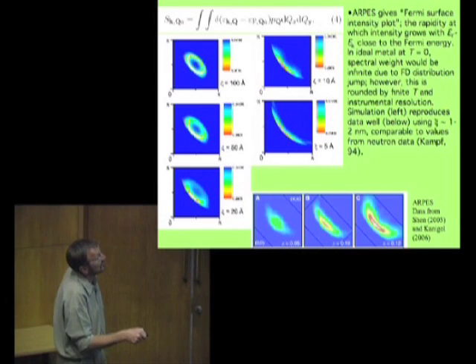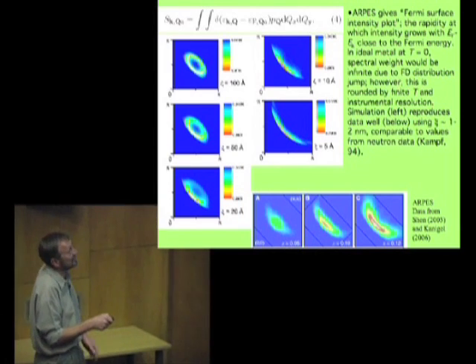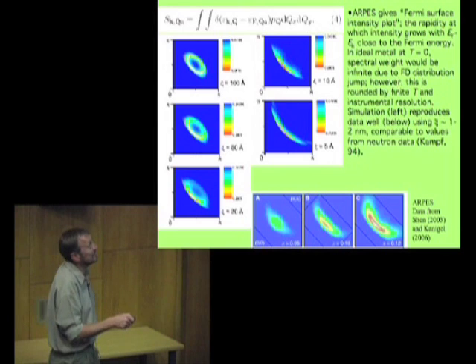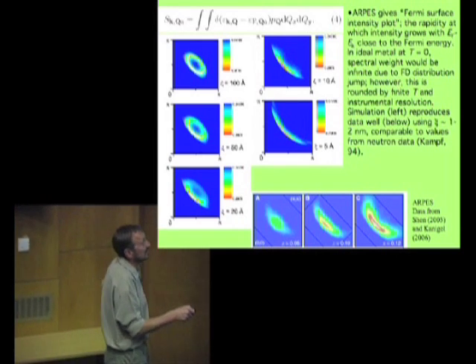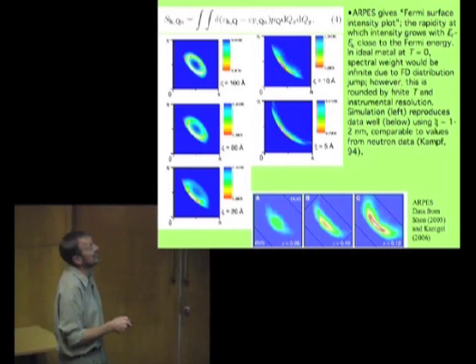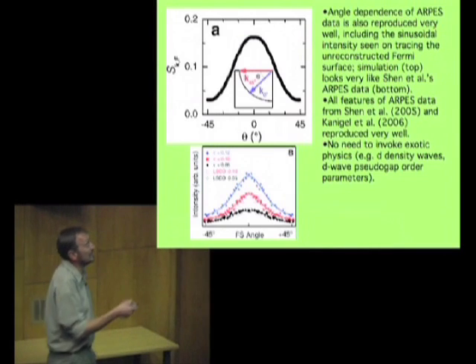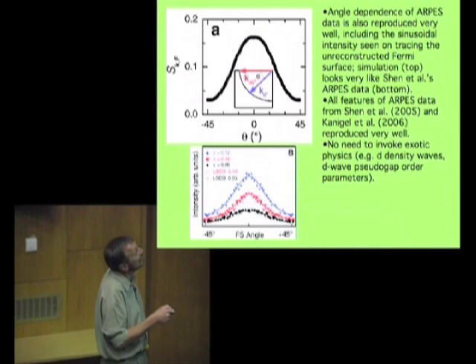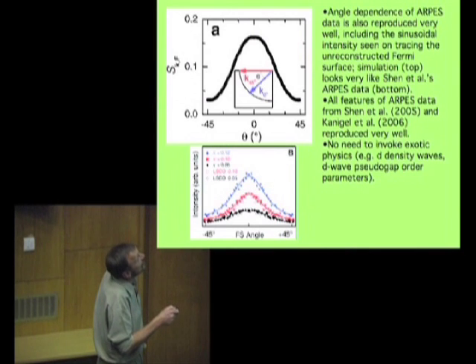So this simulation, which is done just using our measured Fermi surface and that statistical model, looks very much like the ARPES data that people like ZX Shen get. And this is using a very similar antiferromagnetic correlation length to that measured in the neutron scattering. So we think we can understand the ARPES data. We can even model, this is our model of the intensity that you get as you rotate the wave vector across that piece of Fermi surface.